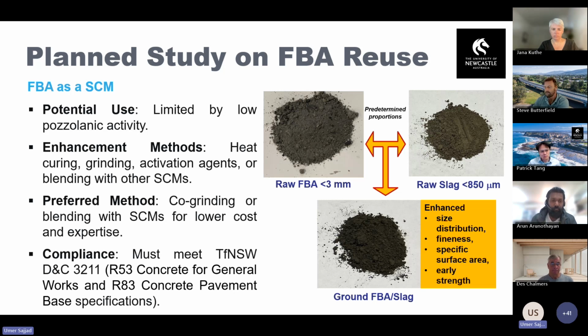And for FBA as an SCM, we have to treat it with different methods. Then we can use it as SCM. As said, it is slightly coarser and it has low pozzolanic activity. So different methods have been opted in research, like heat curing, grinding, activation agents, or blending with other SCMs. What we have adopted is blending with other SCMs, because with heat curing you will not get much benefit, and you can't do the heat curing at the site, specifically for in situ usage of concrete. Heat curing is very difficult to apply.